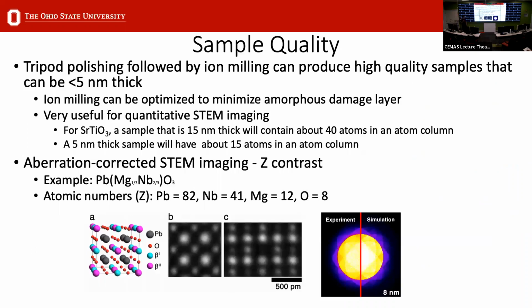So in the past, this is the technique that I actually used for my PhD research. The advantage here is that with the argon ion milling, you can find particular regions in your sample that are extremely thin, which are very useful for things like quantitative STEM. So for example, in a material like strontium titanate, where the unit cell is 3.9 angstrom, if your sample is 15 nanometers thick, you'll have about 40 atoms in that column. If you can get it down to 5 nanometers thick, you'll have 15.